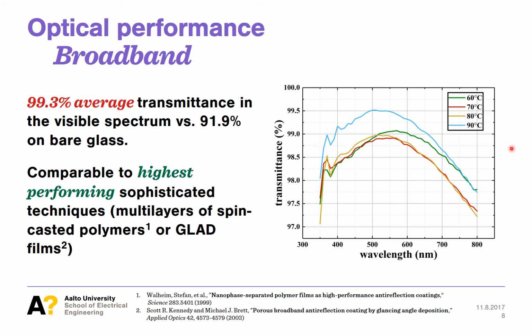We have studied different water temperatures for the grass-like alumina formation and achieved average transmittance of 99.3% in the visible range of spectrum for double-side coated glass. The peak transmittance was 99.5%, around 540 nanometers. We have targeted these wavelengths to have the maximum transmittance by our choice of film thickness. This proves availability of high control over the optical properties of the fabricated coating.